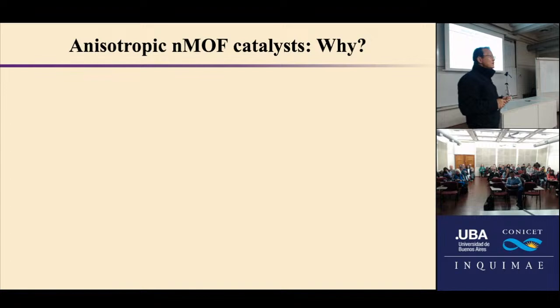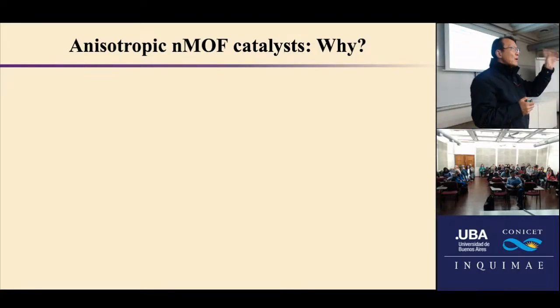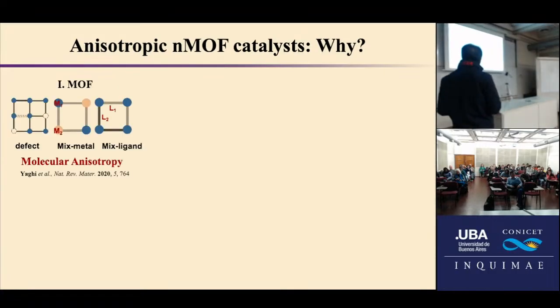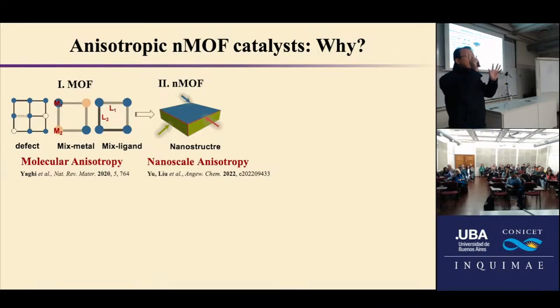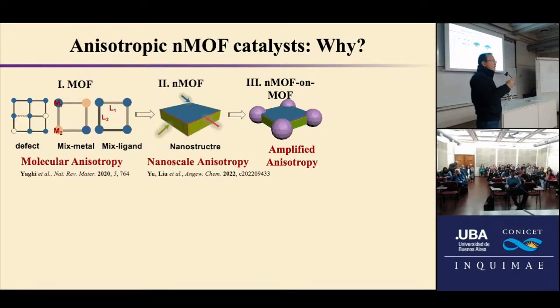So the first topic I'm going to mention is about nanostructured MOF materials with anisotropy as catalysts. Why? Anisotropy means the properties in different directions are different. So we know for MOFs, due to the metal-ligand coordination bond, there is intrinsic molecular-level anisotropy. But if we can control the morphology very well, we know different facets may give you different properties. So this is called nanoscale anisotropy. If we could combine them together, for example, we can grow the second MOF onto the first MOF. We call this MOF-on-MOF. So if this is a MOF-on-MOF nanostructure, this would have the combined molecular and nanoscale anisotropy.